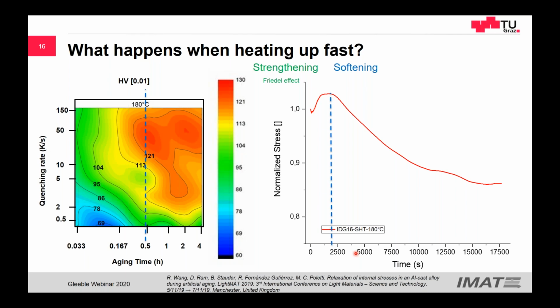At these temperatures, we don't have dynamic recrystallization. In aluminiums, we don't have dynamic recrystallization. We have only continuous dynamic recrystallization. We don't have grain growth, of course. This is everything dynamic. And especially at these very, very low temperatures, we may have some recovery. And this is exactly what's happening.